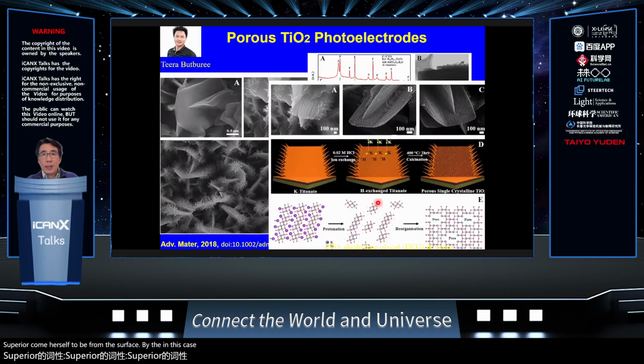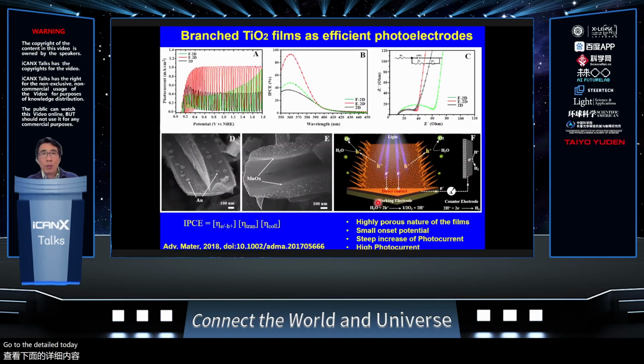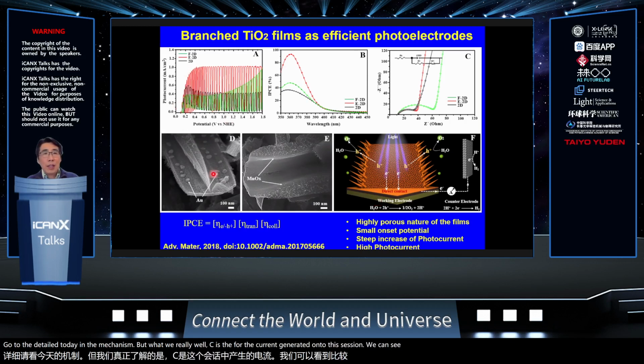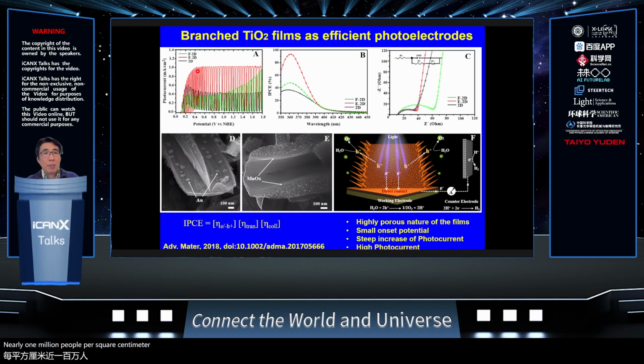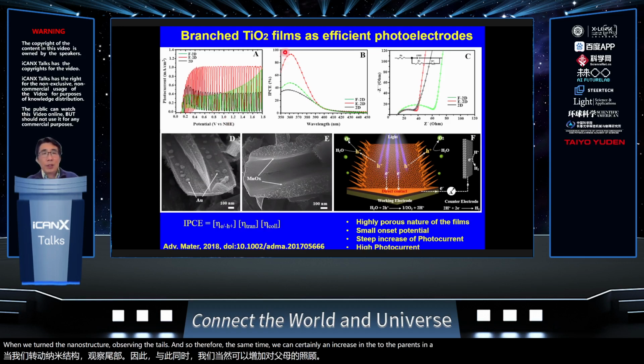In this case, I don't need to go through the details of the mechanism, but what we really want to see is the photocurrent generated on this photoelectrode. Compared with the nanosheet we prepared before, the photocurrent generated here reaches nearly 1 milliamp per square centimeter, which is much higher. This gives us some confidence that when we change the nanostructure of the material, for the same TiO2 material, we can increase the photocurrent density of the system very significantly, several times.